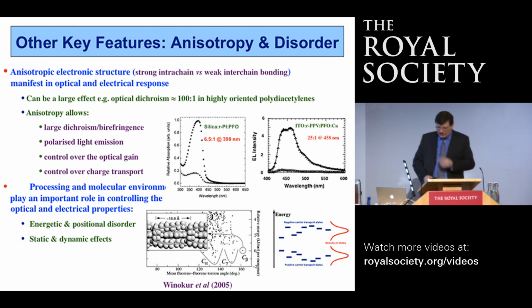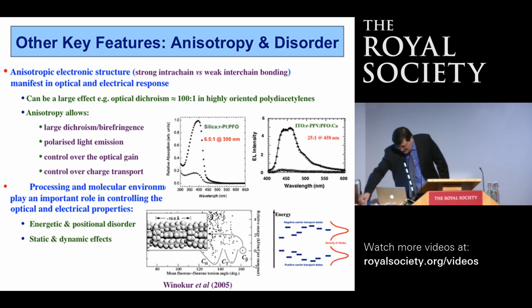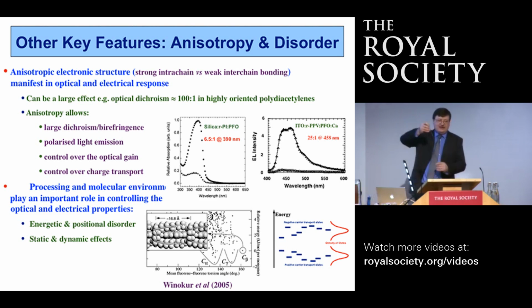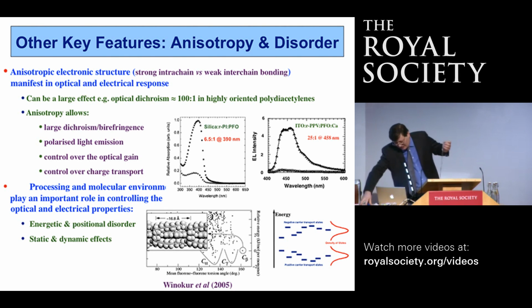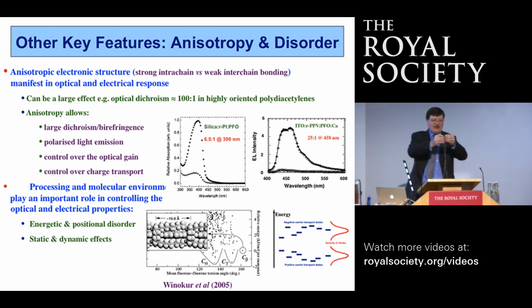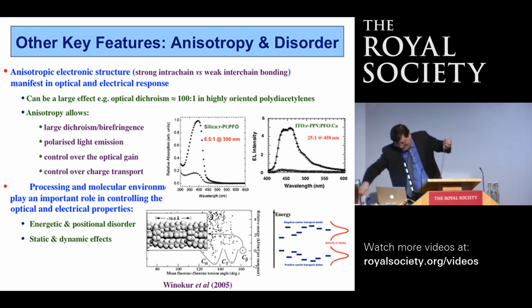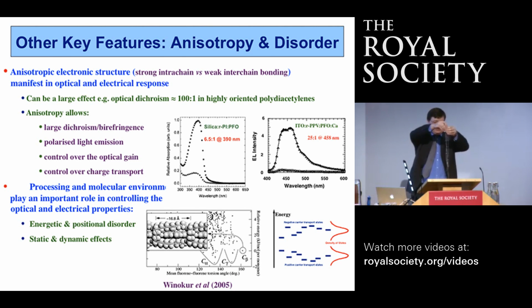What are the other key features? Well, clearly an object like this is anisotropic, so it's long and thin. It basically is an anisotropic object. And that anisotropy is intrinsic to the nature of the material. And in the appropriate circumstances, we can actually generate something which shows highly anisotropic properties. And so instead of having a nice pile like this of polymer chains, if we very carefully take them out and basically align them all up nicely, we end up with a highly anisotropic object.